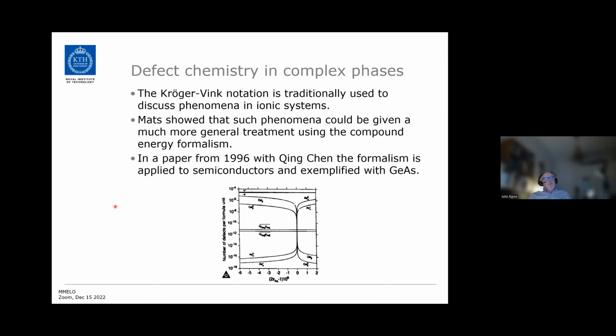But it could also be used to treat defect chemistry, where the Kröger-Vink notation is traditionally used. And Mats showed that by using the compound energy formalism, you could treat these defects in a much more general way. And this is a diagram from a paper by Qing Chen and Mats where they applied the formalism to semiconductors, and this was for gallium arsenide.